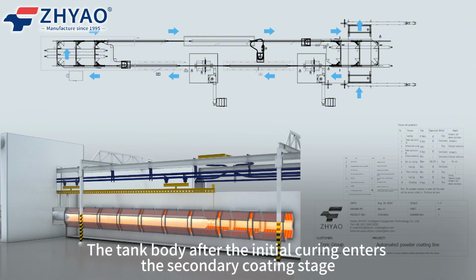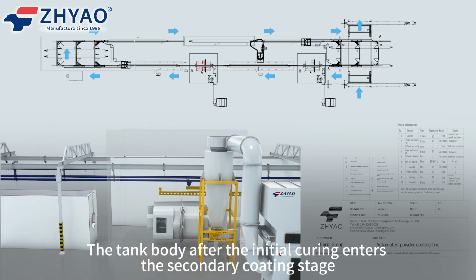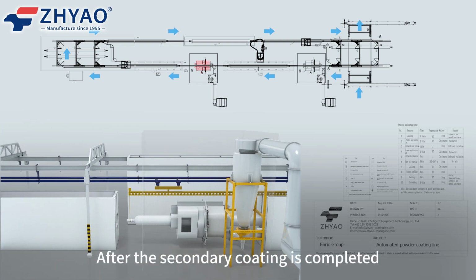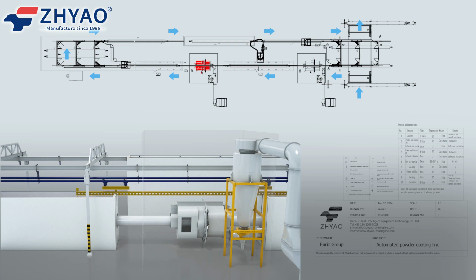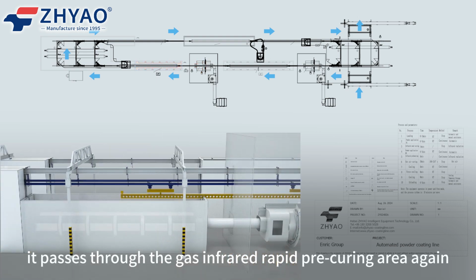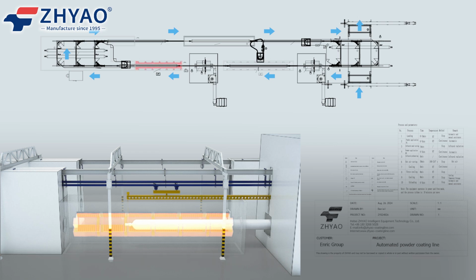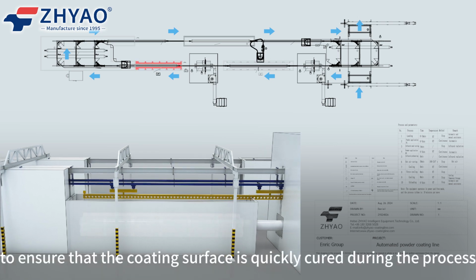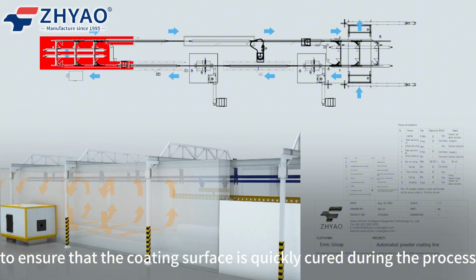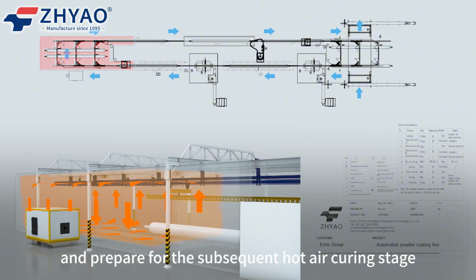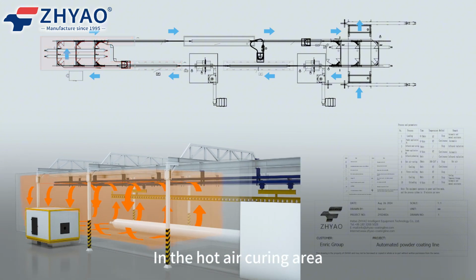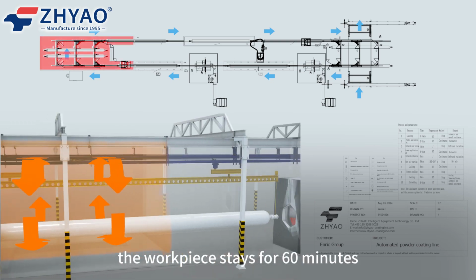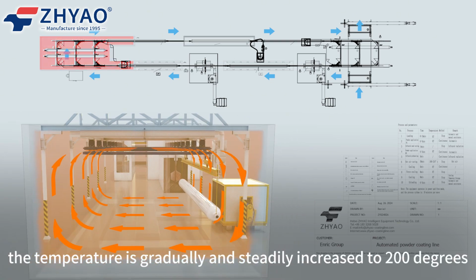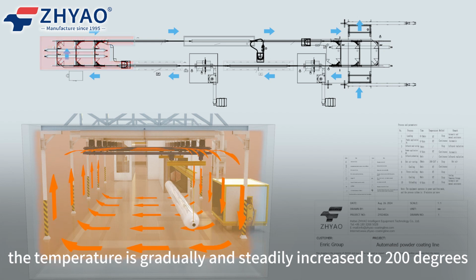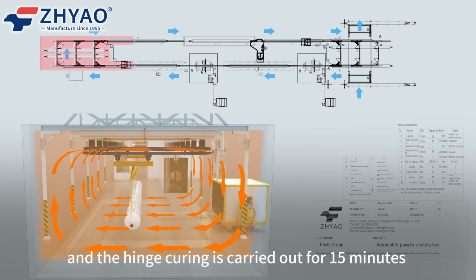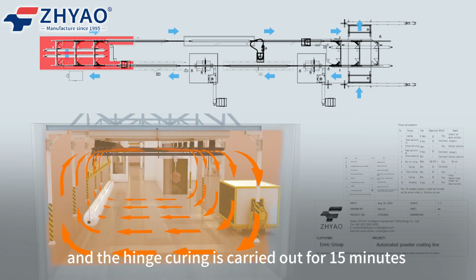The tank body after the initial curing enters the secondary coating stage. After the secondary coating is completed, it passes through the gas infrared rapid pre-curing area again to ensure that the coating surface is quickly cured during the process and prepared for the subsequent hot air curing stage. In the hot air curing area, the workpiece stays for 60 minutes. The temperature is gradually and steadily increased to 200 degrees, and the curing is carried out for 15 minutes.